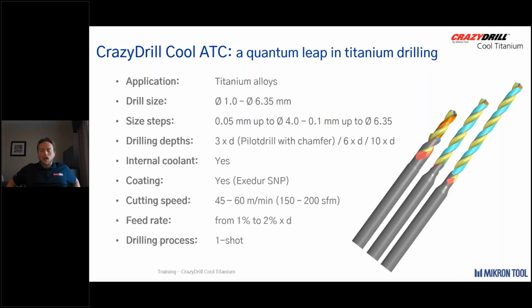In review of these two lines, we showed that case example from the ATC drill. The ATC is on the market. We have a 3 times D pilot, a 6 times D drill, and a 10 times D drill. For diameter range, we start at 1 millimeter. We go to 6 millimeter in metric, 1/4 inch in fractional. We have increments of 50 microns and 100 microns up to 1/4 inch from 4 millimeter.